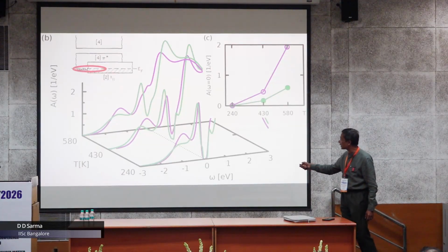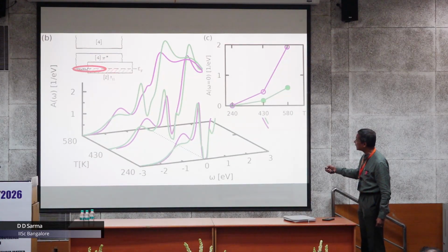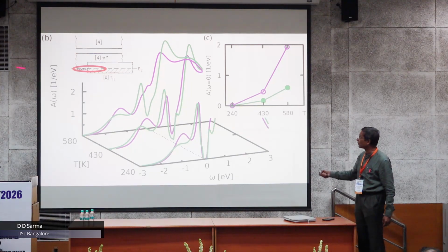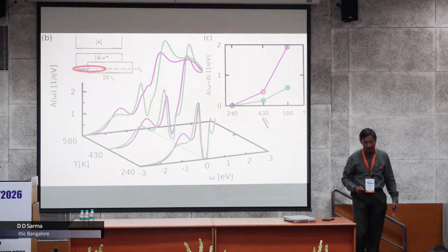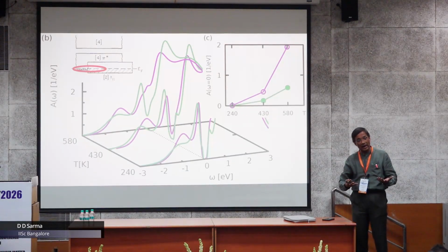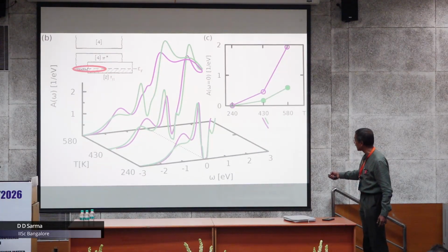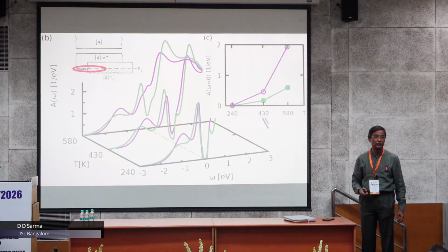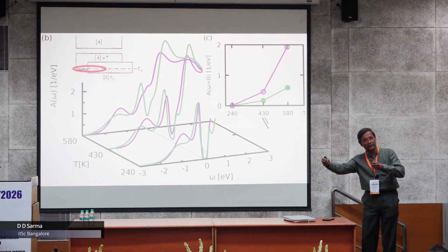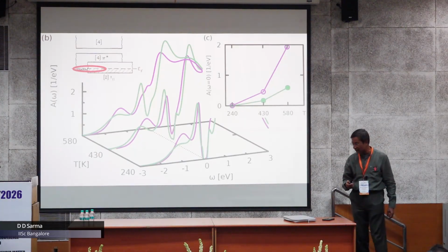What I'll now tell you is what I had introduced earlier, and I'll show you that our theory shows that as we are changing the temperature, this intra-dimer transfer from the sigma to the pi bond, from the A1g orbital to the other orbitals, changes drastically. And I'll show you more quantitatively in a few slides later. That means that the underlying electronic structure itself is changing drastically, completely changing the scenario as the temperature is increased, because of this intra-dimer transfer of electrons within the dimer from one kind of orbital to another kind of orbital, giving rise to rather incoherent but large intensity spectral weight at the chemical potential.